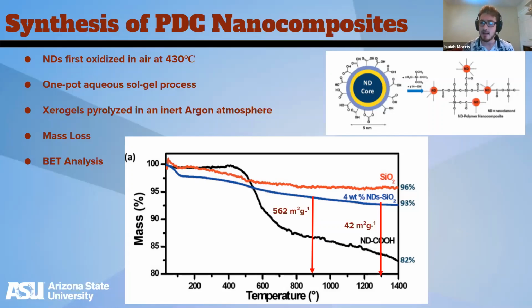Now, there are a few pieces of data that I want to point out. For starters, the mass loss within the nanodiamonds themselves. As you can see here in this blue curve, there was around a 4% mass loss within the nanodiamonds, but that can be largely attributed to the loss of functional groups as well as water from the nanodiamonds themselves. Another important thing to note is the BET analysis, the specific surface area of the xerogel and of the composite itself. At room temperature, the xerogel was found to be relatively mesoporous, but its max surface area was found after pyrolysis at 900 degrees Celsius, yielding a value of 562, which is rather large.